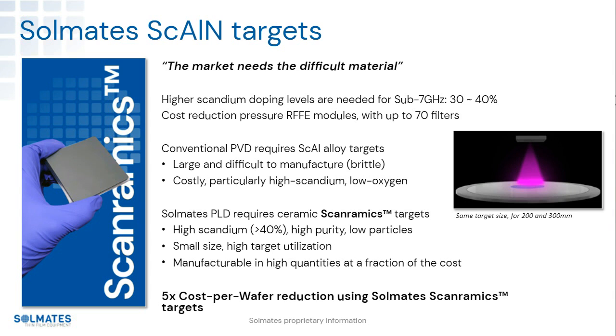So we've developed our own ceramic target. And the word ceramic here is important. It's not an alloy, right? What we do is we have a scandium-doped aluminium nitride. The nitride's in there. It's a ceramic target, and we do a stoichiometric transfer. So the source material, we transfer it to the wafer. It's the same. And therefore, it's fundamentally different.